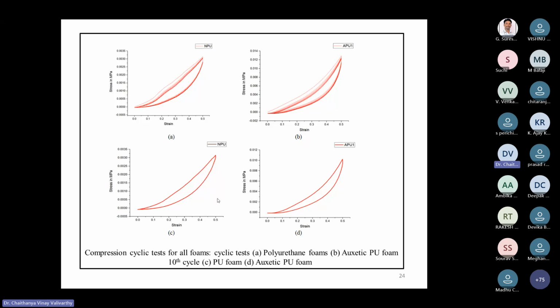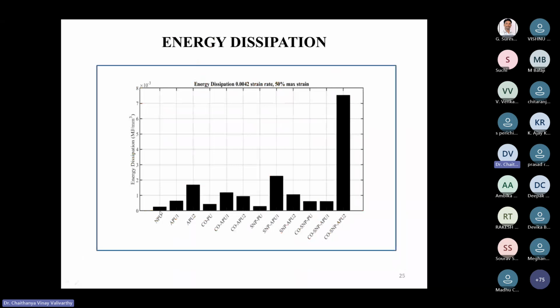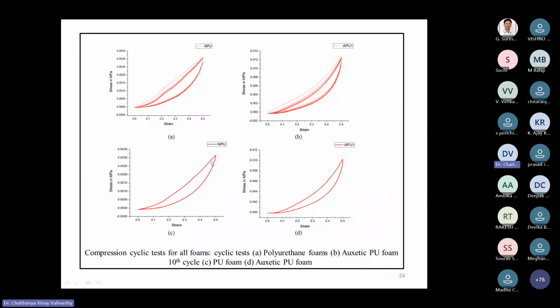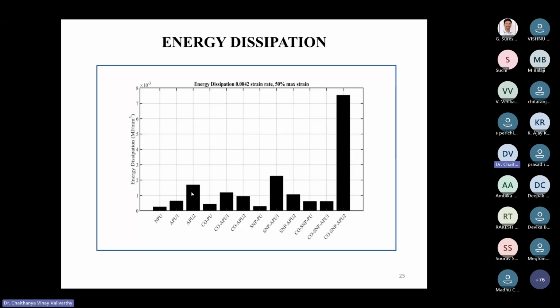So here we have two behaviors in the cyclic test: one is hyperelastic and the other is viscoelastic. Viscoelastic means there is a loading and unloading curve. If the loading and unloading curves are on the same path, there is no viscoelastic component. But here there is a gap between the loading and unloading curves, so we can say there is a viscoelastic component. Regarding energy dissipation, when we add nanomaterials like SNPs and CO as additives in the PU foam fabrication and convert the foams into auxetic foams, we got very high energy dissipation for CO, SNP and APU foams.